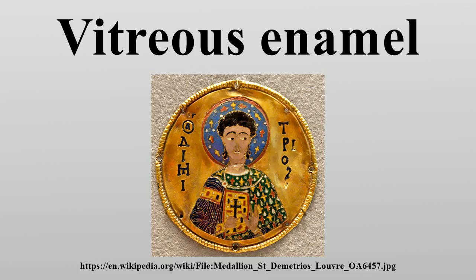Industrial enamel application. On sheet steel, a ground coat layer is applied to create adhesion. The only surface preparation required for modern ground coats is degreasing of the steel with a mildly alkaline solution. White and colored second cover coats of enamel are applied over the fired ground coat. For electrostatic enamels, the colored enamel powder can be applied directly over a thin and fired ground coat base coat layer that is co-fired with the cover coat in a very efficient two-coat, one-fire process.